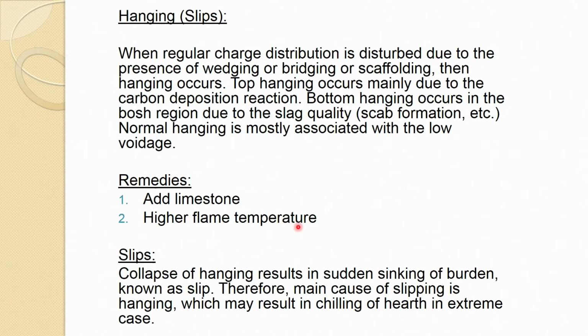Remedies: add more limestone, higher flame temperature. I am not talking much about this because we have talked about it. In fact, we have discussed with some figures how this bridge is forming and hanging occurs, and below this the void space is created, and when it is unable to withstand that pressure, suddenly the whole chunk slips down, and that is where slips come. So, collapse of hanging results in sudden sinking of the burden, known as slip. Therefore, the main cause of slipping is hanging, which may result in chilling of the hearth in extreme conditions. So, this is very important, hanging and slip, and we had discussed this before. So, I am not discussing much. You can go back to some of those slides and have a look at it.